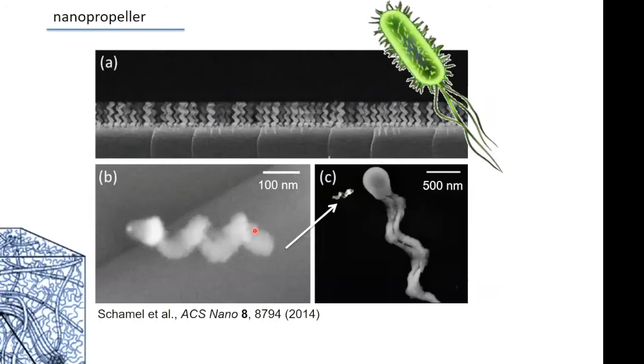And the other thing which is nice in these artificial systems is that we're not restricted to the systems that nature builds. Nature has a certain size for bacteria, because when they are too small, it makes no sense. Then diffusion is more effective, but it doesn't stop us. This here is a propeller of the size of a bacterium. And we can also build things which are much, much smaller than any swimming microorganism. And then we can have, for instance, here a width of 70 nanometers, which means it can be small enough to actually navigate real tissues.